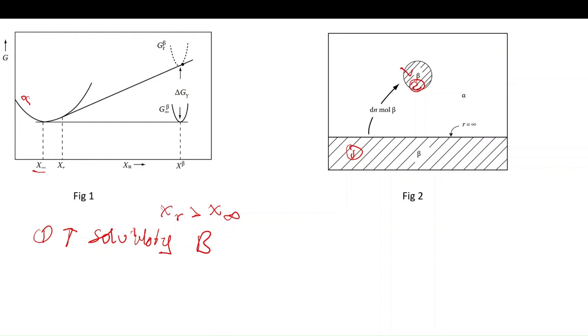But if we go on increasing this Gr, now this is a very dangerous situation because the system will try to minimize its energy. What will happen is it will get engulfed by the bigger precipitates. As you try to decrease the r and make it more and more finer, it can also get eaten by bigger precipitates.